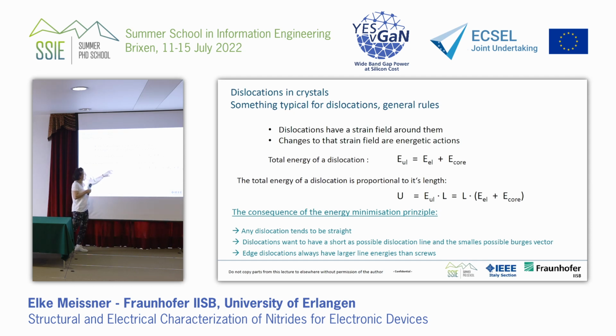And the dislocation energy is proportional to the length of the dislocation. So as a consequence of the minimization principle, the dislocations always tend to be straight. This is what the threading dislocations are doing. Of course, there are also geometrical constraints from crystallography reasons, but the dislocations won't go like this through the crystal, because this makes, from an energetic point of view, no sense. Which is good, because at least the dislocations want to be as short as possible.